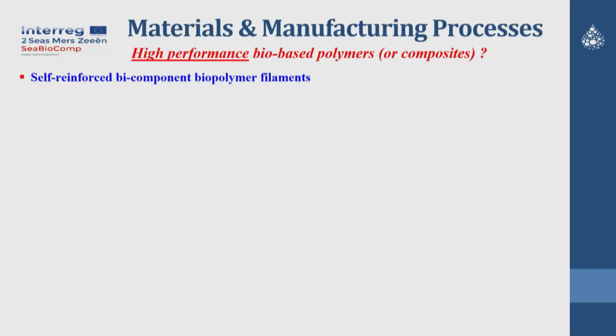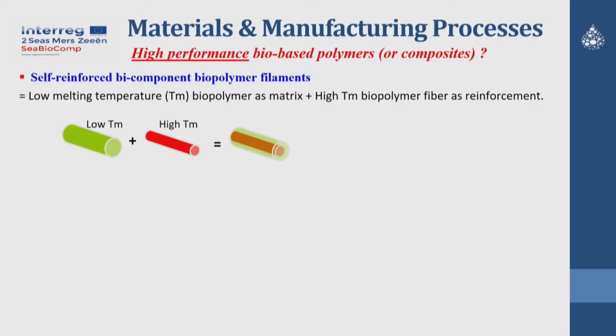The basic concept is that within a single filament, we integrate two different biopolymers. Outside is the low melting temperature biopolymer, and inside is the high melting temperature biopolymer, the high Tm biopolymer. Inside these polymers, all the molecules are aligned in the same direction to achieve high mechanical performance. Then these two different materials are combined into a single filament. These single filaments are then woven into a kind of non-woven preform ready for compression molding. This is the first material that we have developed.